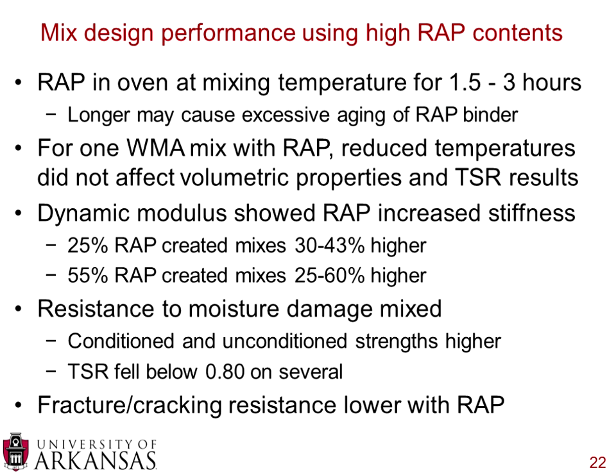When you're thinking about how you perform your mix design and if you need any sort of adjustments, they recommend putting the RAP in the oven at the mixing temperature. Now, you saw earlier in the presentation a recommendation of having the RAP going no hotter than 110 degrees Celsius. Here, mixing temperatures can be significantly higher than 110 Celsius. If you're using a PG 58-28, you can get mixing temperatures up to 155 degrees Celsius.